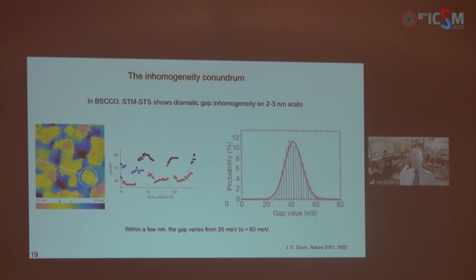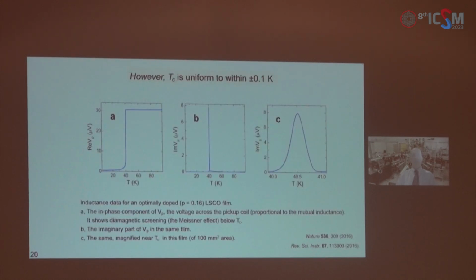Well, in some sense, something like this was seen by STM already in 2001, 2002, reporting incredibly large variations of the gap by up to 300% and varying on the scale of just a few nanometers. And that's where we have another puzzle or paradox.